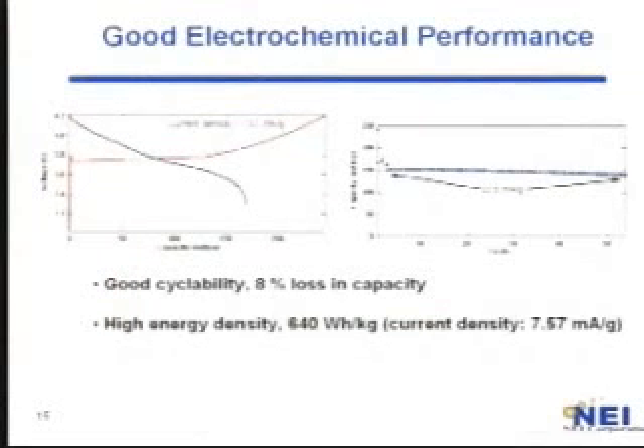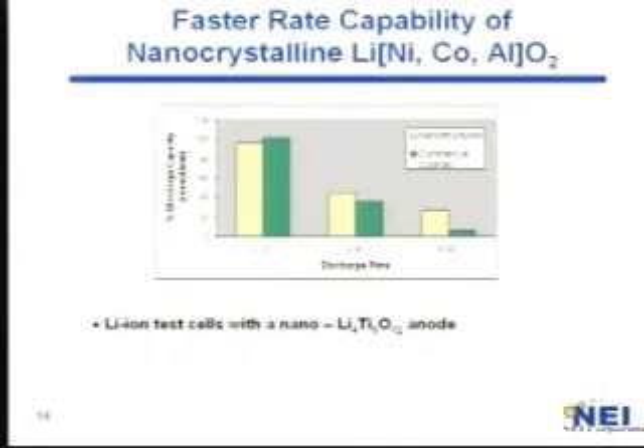Before I show the comparison, I just wanted to show it has good cyclability, and the capacity of this material is around 160 milliamp hour per gram, which is almost close to the theoretical number at low current densities, of 640 watt hour per kg. Here, this is the comparison between the nanocrystalline material versus the commercial material, which is exactly the same composition.